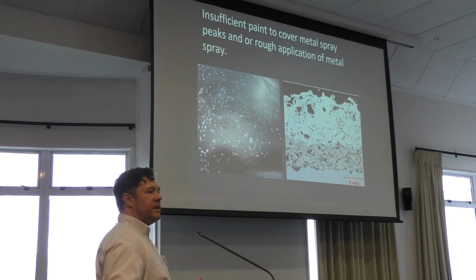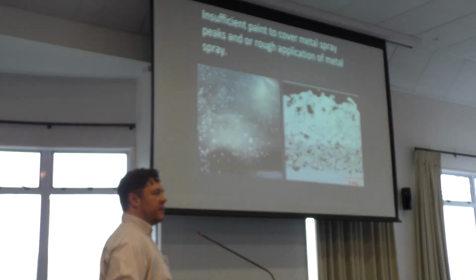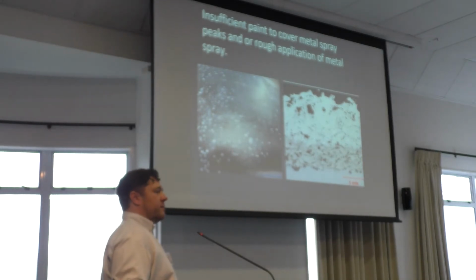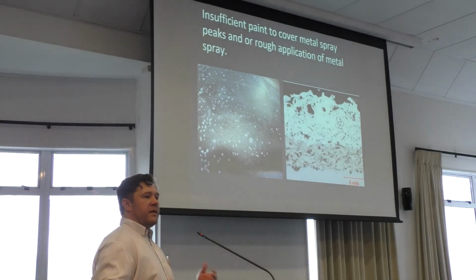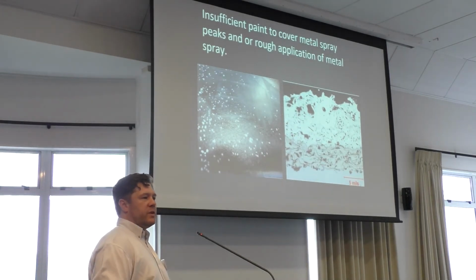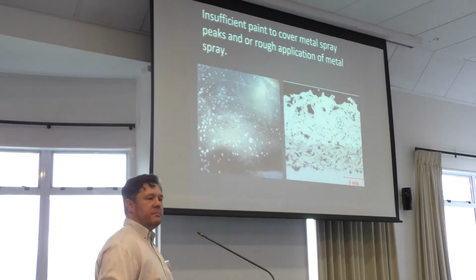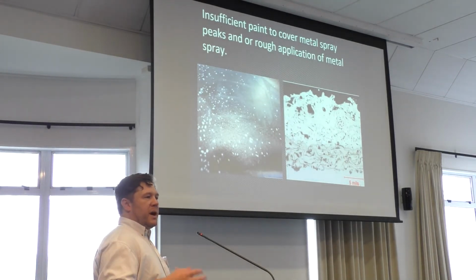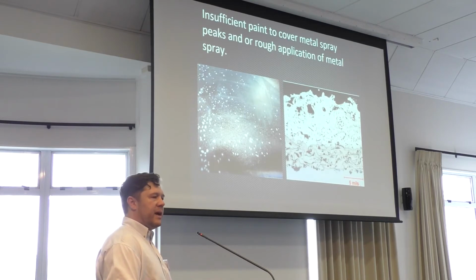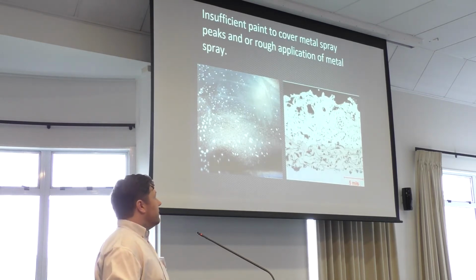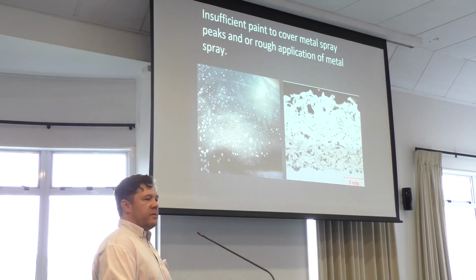Typically, if you've got a machine that goes really, really fast, you're going to have a more coarse coating than the slower machines. That's just a fact of life. There's a ratio, if you like, of air to wire. So if we're melting wire at 70 kgs an hour and we've got 110 CFM of air to atomise that molten wire and propel it at the job, those particles are going to be larger than if you're melting 30 kgs an hour and using the 100 CFM to atomise it and propel it at the job. The wearing tips and wearing air caps and so on create variance in this as well. So you're relying on the operator to pay attention to what he's doing and make adjustments or change the parts if the surface becomes too rough.